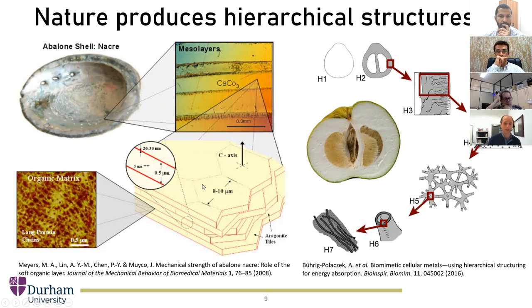So when the crack goes in the hard material and it hits the soft medium, it kind of gets stuck, maybe needs to look for a different route. And this made me think of this technique that is sometimes used, say, in steel bridges, right? If there is a crack and we want to stop it, we can just drill a hole at the tip of the crack, and suddenly we release the stress intensity from the point to a larger region, and the crack stops there, needs to find a different route somewhere else. So this seems to be a quite effective mechanism, this crack deflection, but it's based on the stiff and soft. So it seems that nature likes such contrasts for fracture toughness.